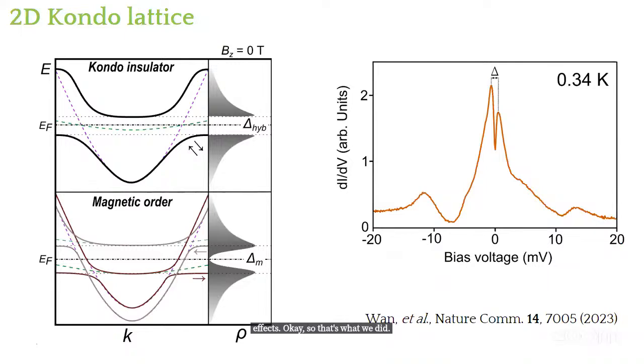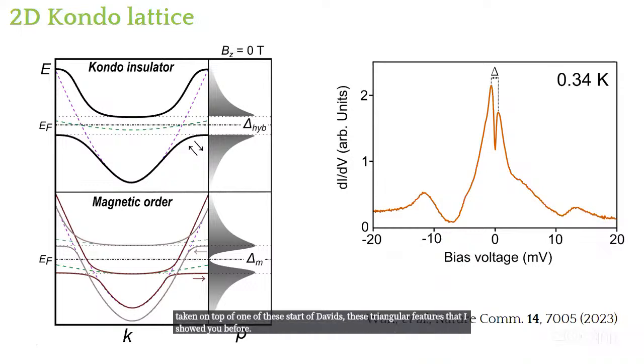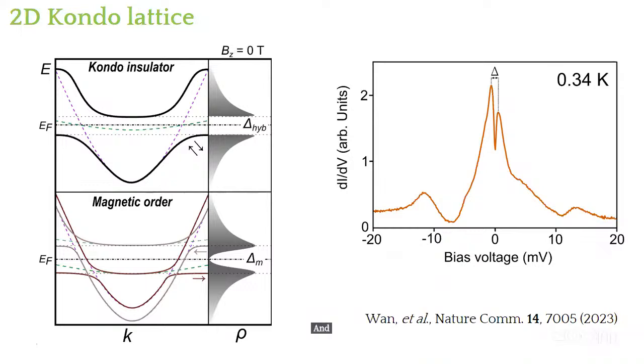Basically, again, this is a dI/dV curve, local density of states, taken on top of one of these Star of David, these triangular features that I showed you before. And this is how it looks. There's a huge increase of the density of states at the Fermi level, and you can see there is a gap-like feature exactly at the center of the density of states. So no surprises, which is what we expected in terms of density.